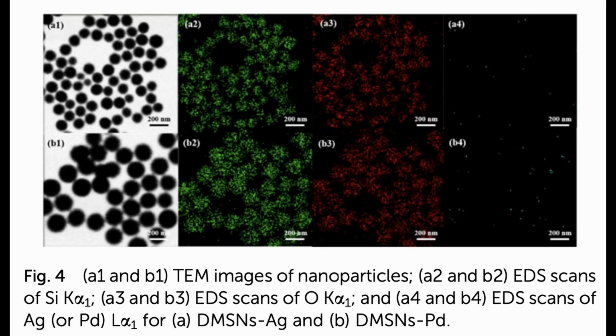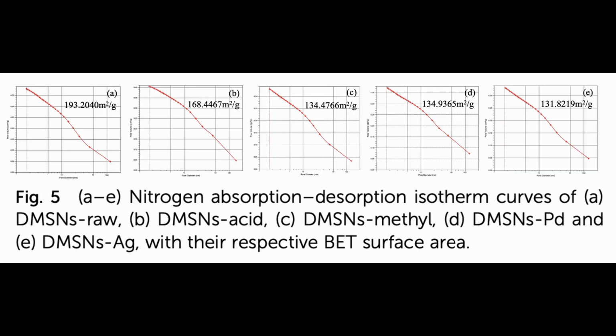Energy dispersive X-ray spectroscopy, EDX, then elucidates the elemental composition of the spheres, with each element identified by their characteristic X-ray spectrum and suggesting that silver and palladium metals are indeed loaded on the catalyst. Next, the nitrogen adsorption-desorption isotherm tells the specific surface area by measuring the volume of nitrogen gas adsorbed on the surface, showing the insanely large surface area to mass ratio.